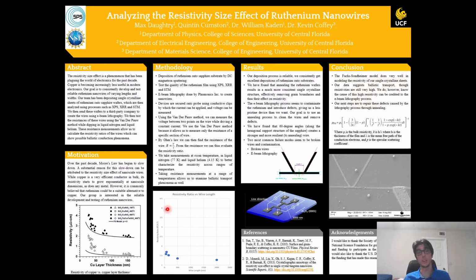Also, the team has found in the past, before I had joined, that leaving the ruthenium nanowires at 60-degree angles from each other results in much stronger wires. The reason for this is that the crystalline structure of the underlying sapphire substrate is hexagonal. So at angles of 60 degrees, the ruthenium wires are lying more directly on that support structure, which means that it's more resilient to annealing, which will be an important process in removing any defects that were previously introduced by the e-beam lithography process.